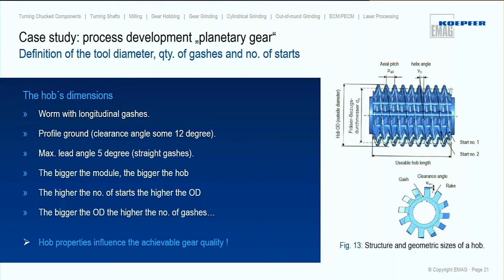And the question is now, how do we design our tool? And we will later on apply different macro geometries of hobs and see what will be the impact on our final result. Generally, there are a couple of rules. The maximum lead angle for a hob shouldn't overstep 5 degrees. The bigger the module, the bigger the hob will be due to this angle. And the higher the number of starts, the bigger the hob diameter will be too. And of course, the bigger the diameter, the more gashes we can put onto the hob.